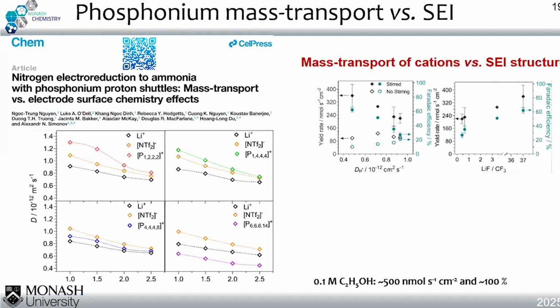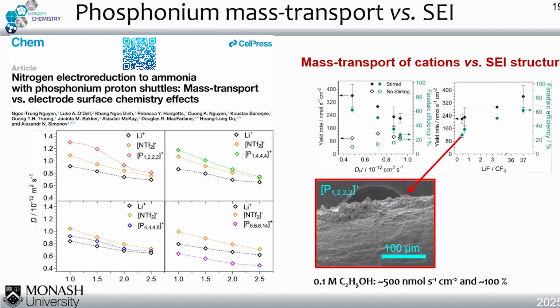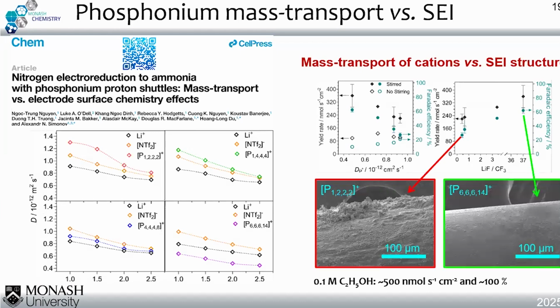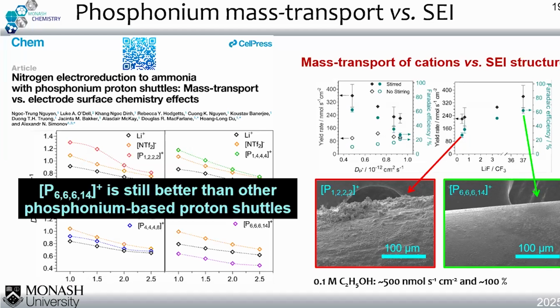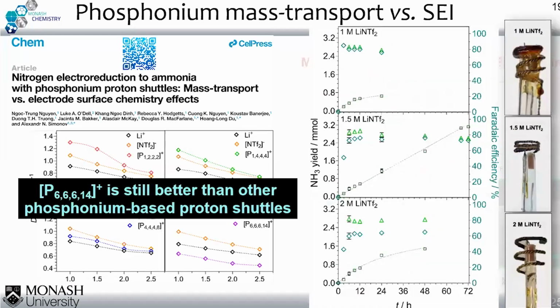So the longer alkyl chain actually performs better. And then we look closely at the surface, and it's very interesting that the longer alkyl chain can produce a very smooth and uniform SEI layer. That means the SEI is very important for the lithium NRR. To balance the mass transport and the SEI, we tune the lithium salt concentration, and with the right concentration, we can achieve continuous improvement of the ammonia yield and the Faradaic efficiency up to 80%.